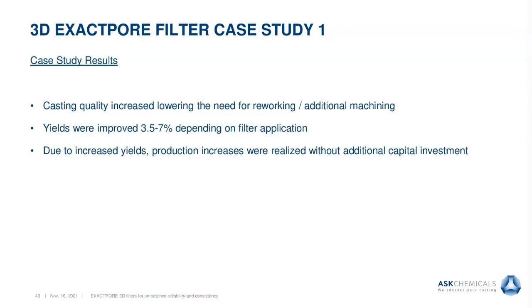The final result at this customer was that casting quality increased, lowering the need for rework and additional machining, while yields were improved 3.5% to 7% depending on the filter application or orientation. Due to these increased yields, production increases were realized without any additional capital investment.